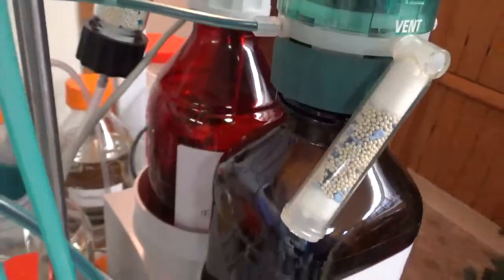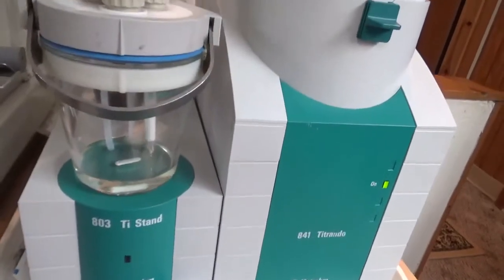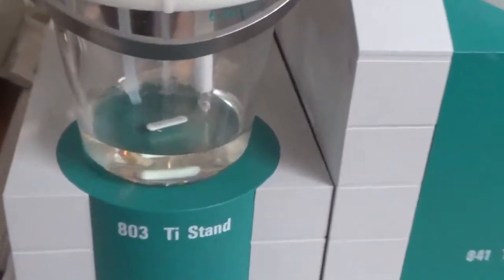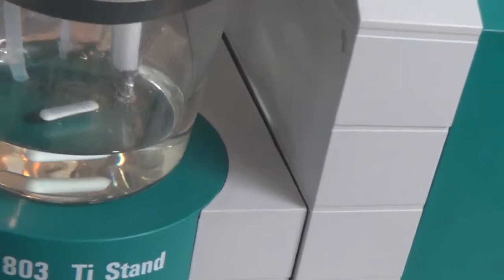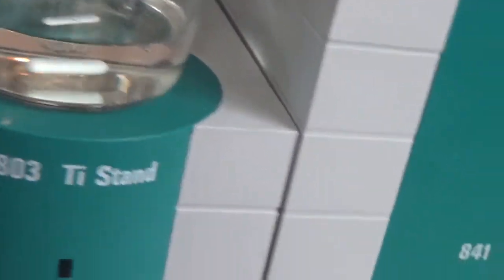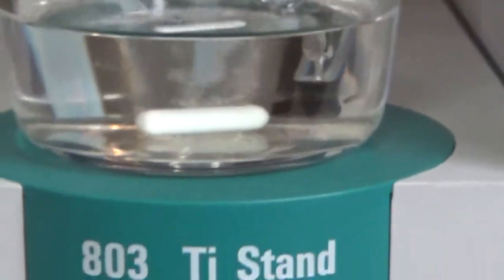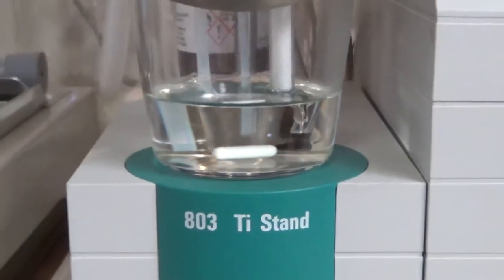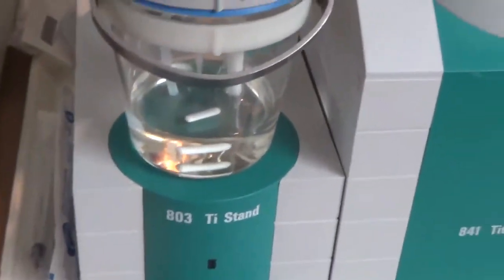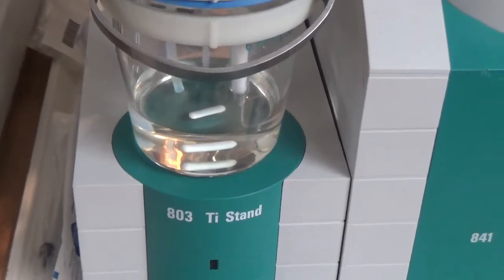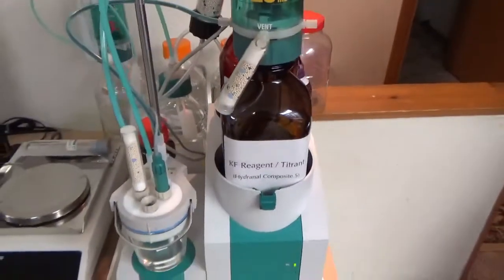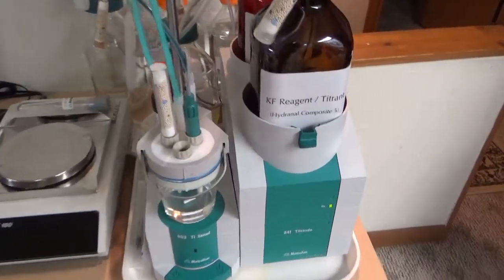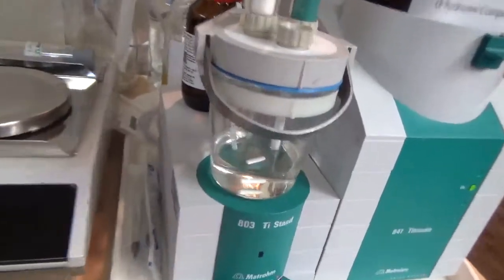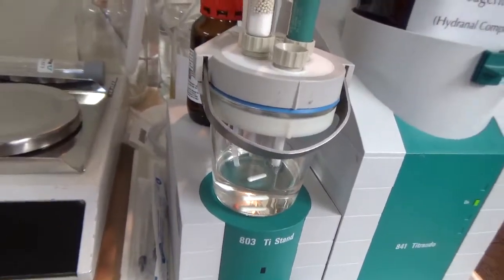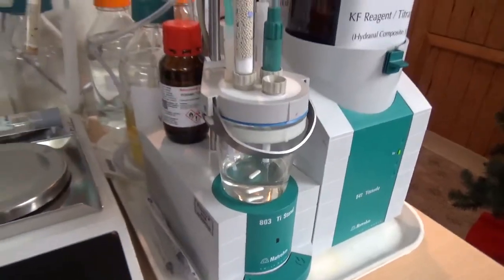and the solution comes from the bag bottle, the ethanol bottle, until the tip of the electrode. Here we are using a double platinum electrode, until the tip of the electrode is under the ethanol. And then during the conditioning period, it removes the moisture that is present in this ethanol solution by adding iodine Karl Fischer reagent to react with the moisture and consume the moisture that is present before we add the sample or the standard. This solution, it removes the moisture.